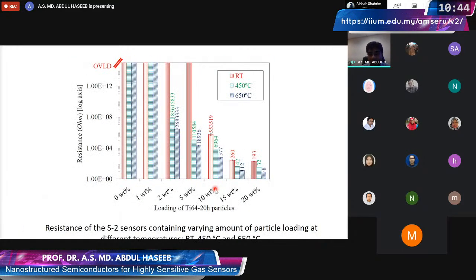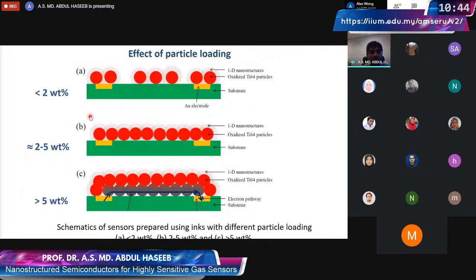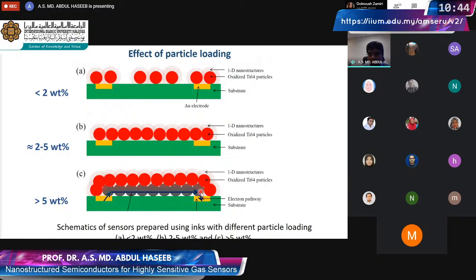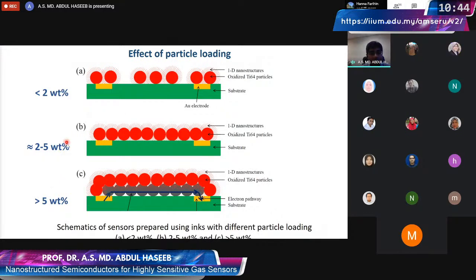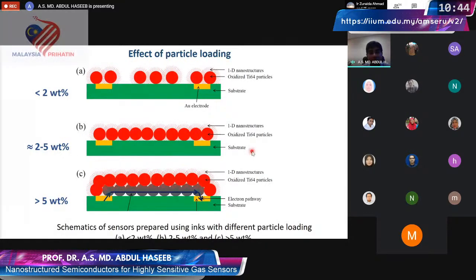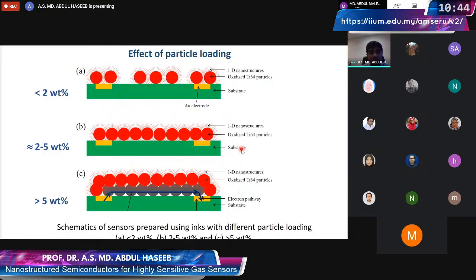And this is the mechanism that we propose here that is happening at low concentration of particles. What we have is that the gaps in between the particles remain, so we don't have a continuous conduction path, and as a result, the resistance is very high. And on the other hand, if we have very thick layers, the layers beneath the top surface actually get reduced in reducing environment, and they become metal and they become active now. And they just short this whole thing. So this is also not good. And this is the ideal condition that we want to have, where the particles just touch each other at the nanowires, and the conduction happens through the nanowires, because these are the active material that we want to have for our gas sensing.